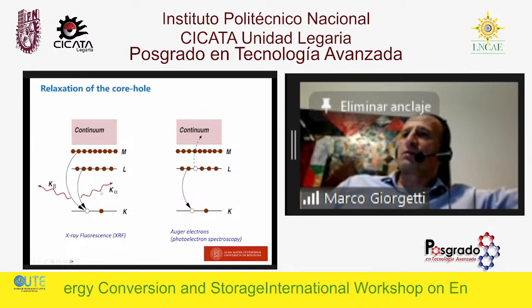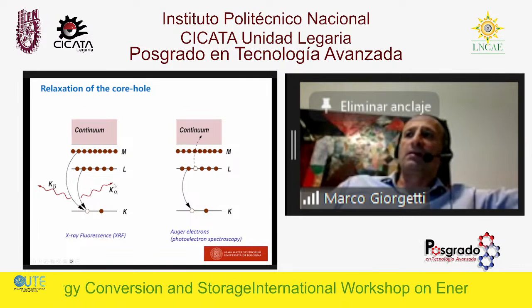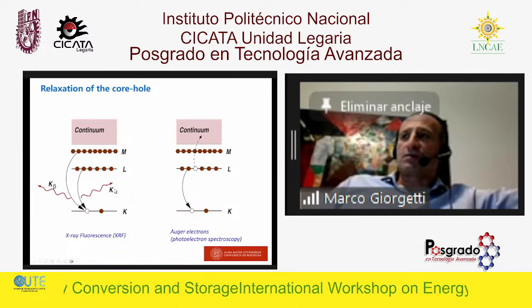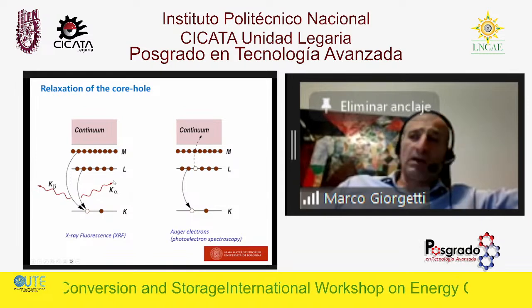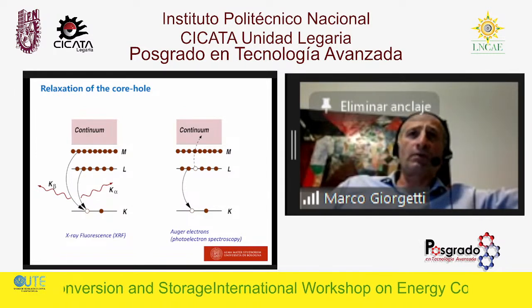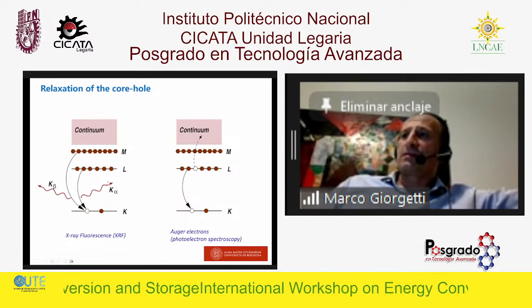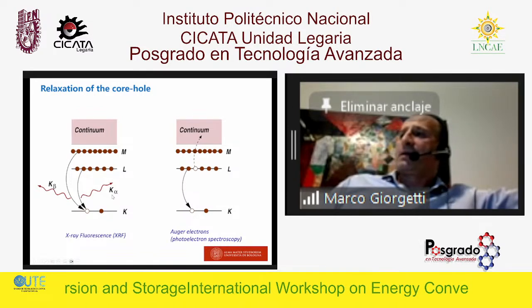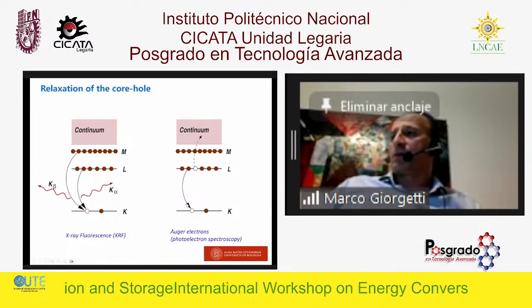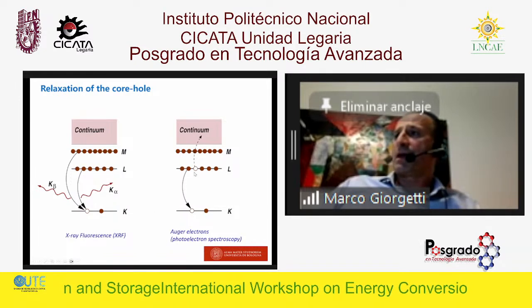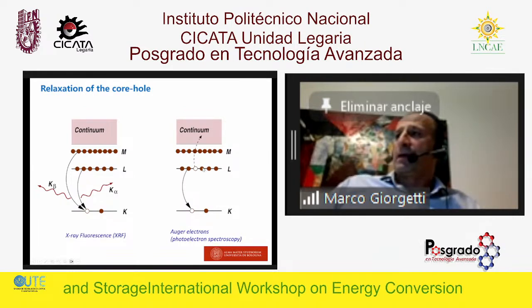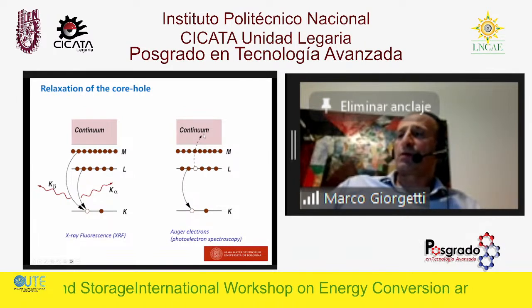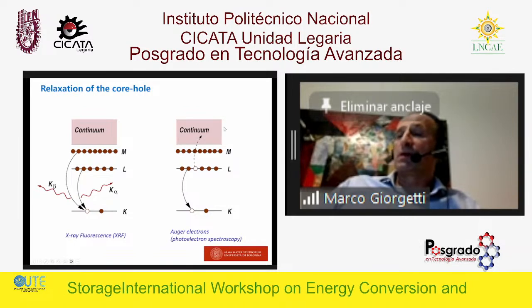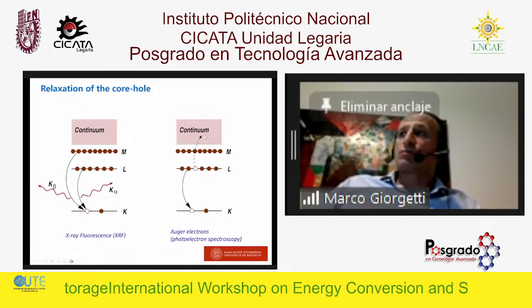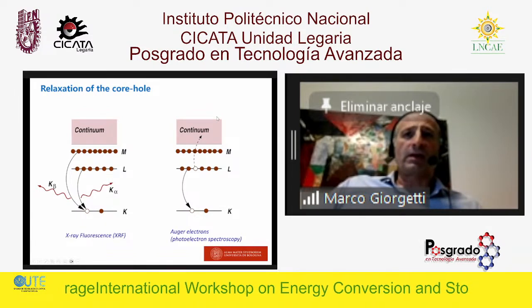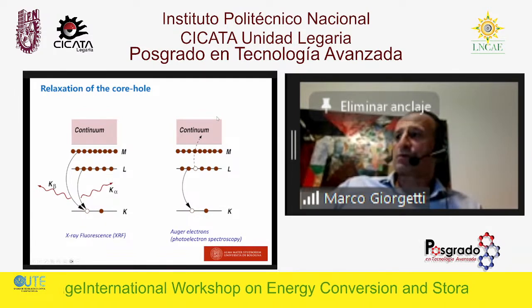Then we have the simultaneous emission of K alpha or K beta. For instance, we know the copper K alpha radiation is one of the very important ones, because a lot of X-ray machines around the world generate this K alpha radiation. And the second possibility is the Auger electron, where this energy gap is used to promote another electron from the L states to the continuum. So basically, when we measure the kinetic energy of these photoelectrons, we open up the whole family of techniques called photoemission spectroscopy.